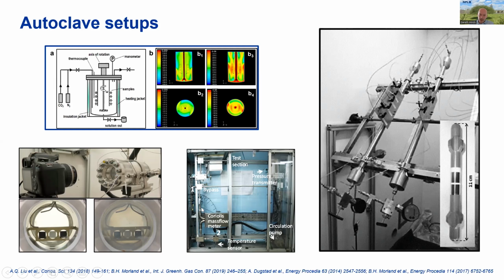Another type is the flow loop. These are typically the most expensive type of autoclave setup and the most challenging to achieve conditions similar to what you see in the pipeline. So here we typically have thinner, longer autoclaves with high pressure pumps to pump the fluid around. And that simulates most closely the conditions that you might see in a pipeline.